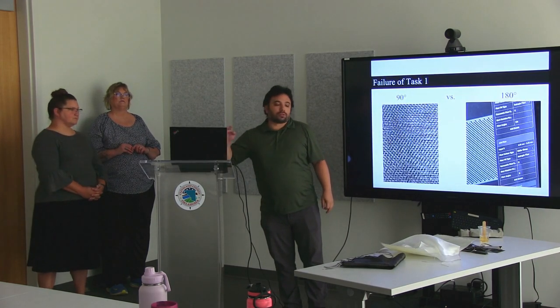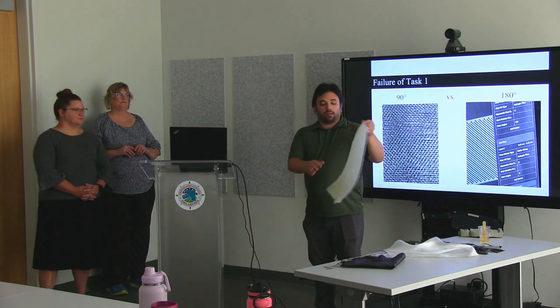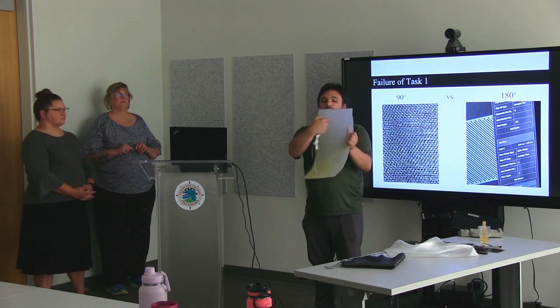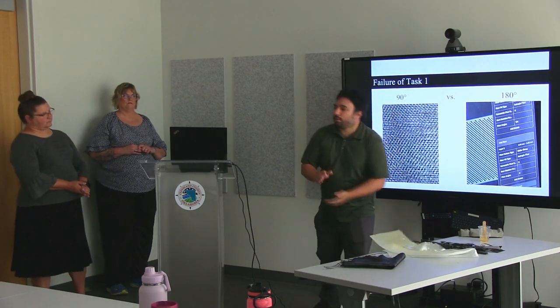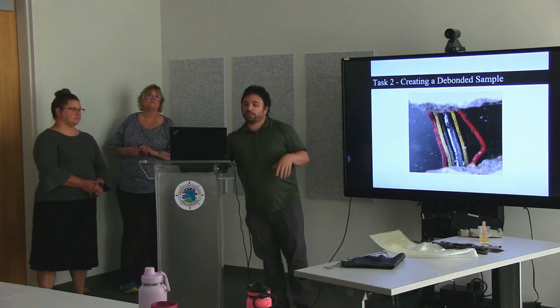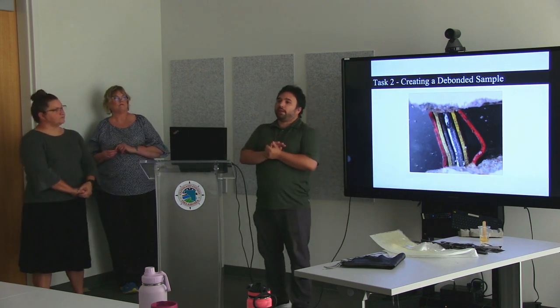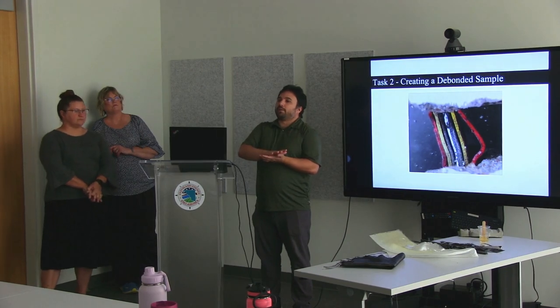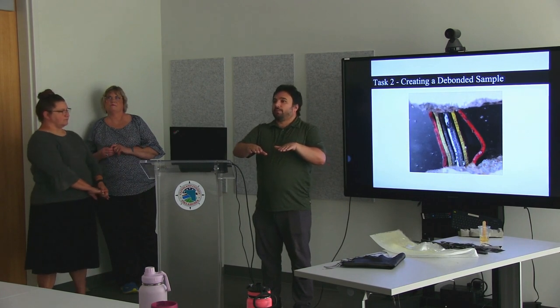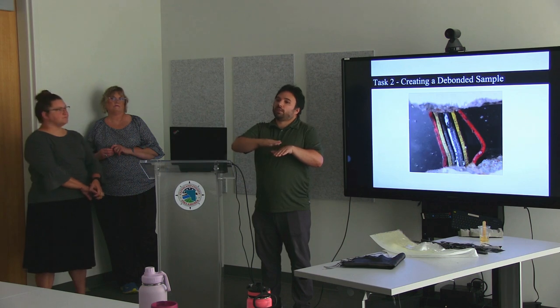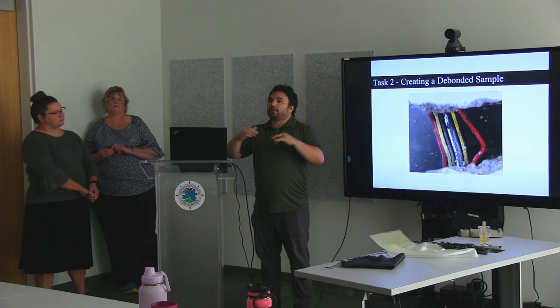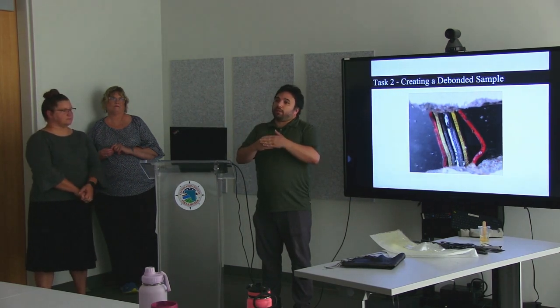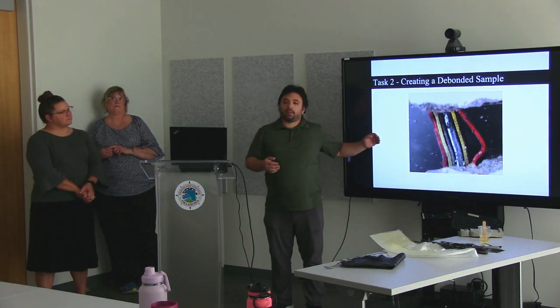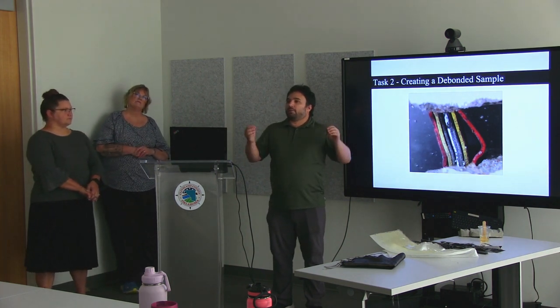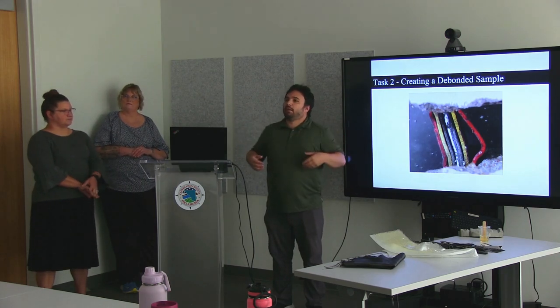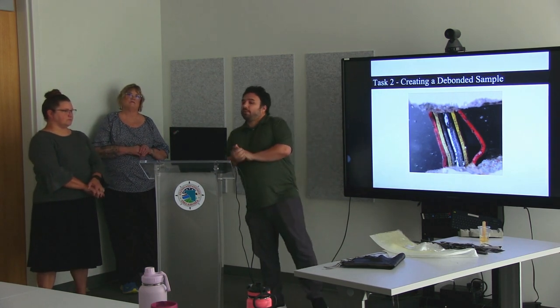So in our specimen, we use the wet layup with the 0 degree and the 45 degree, and the others are just 3D printed. But as I told you, we don't want them bonding to each other, we want them to debond. Dr. Vemuganti tried a way: when it's printing, stop the printing, put in dry ice to make it cold, then resume the print. Without bonding, they are not connected, so they do not fail together. It's not a catastrophic failure. But I think it doesn't work well, because you have to stop, fill all the part with dry ice, and wait for it to get cold.